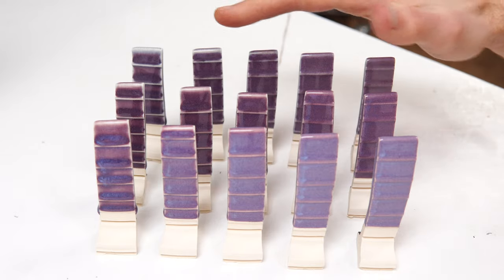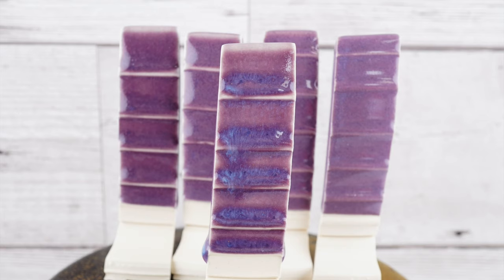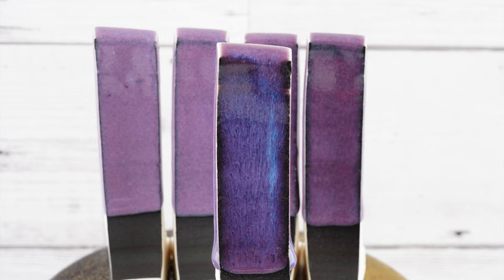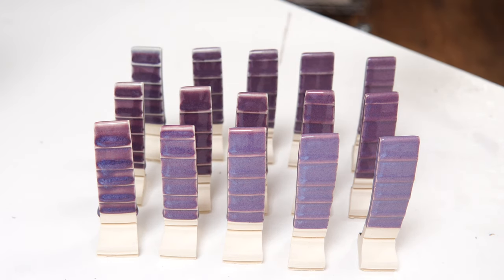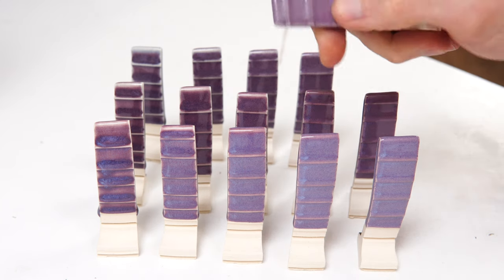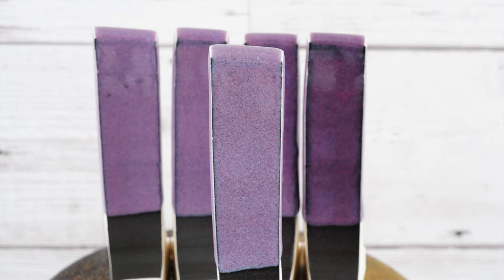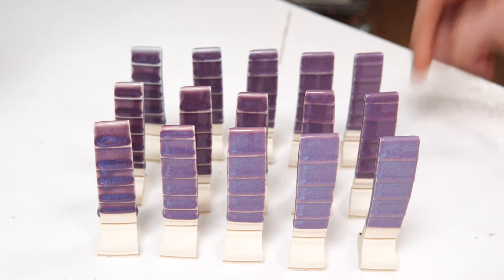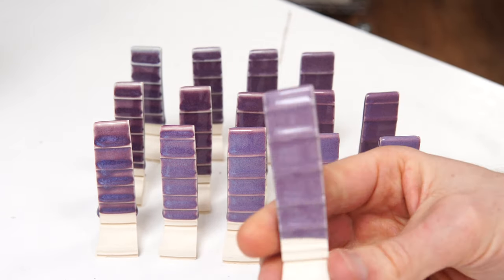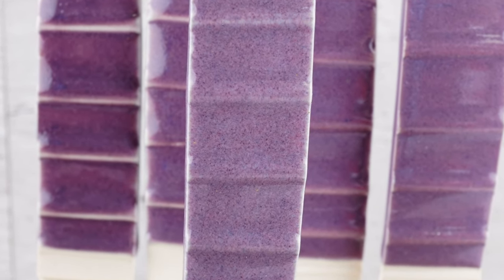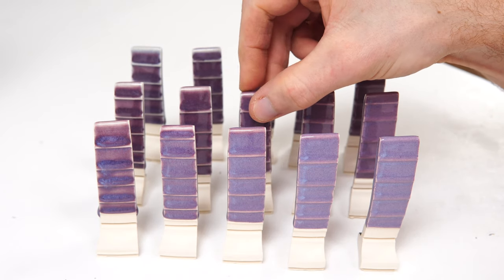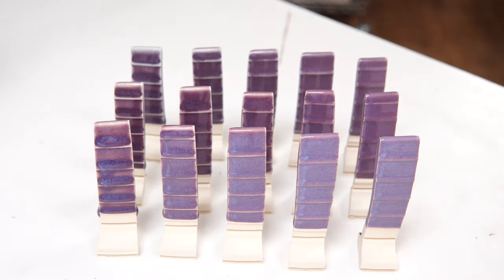I personally, from looking at these tiles, prefer the upper corner. I like the movement that you get down here in the bottom corner - it keeps the color. But I prefer the overall finish up in this corner where they're glossy and smooth, whereas these are a bit more pitted. It's a nice opaque finish. The whole point of adding the bone ash is to get the phase separation to make it more mottled, which these do still have. It's not so obvious, but when you really zoom in you'll see there's a texture to them which is preserved better in the top corner. These tend to be a bit more blurry.